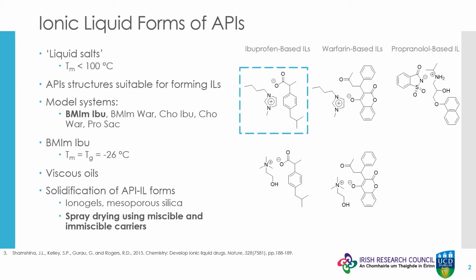Ionic liquids are a class of compounds with a huge amount of promise for simultaneously addressing the issues posed by poor aqueous solubility of APIs and the issues of solid-state instability by forming a thermodynamically stable liquid form of the drug. As APIs are often large, bulky, asymmetric molecules containing aromatic and ionizable groups, they readily lend themselves to forming ionic liquids. To do this, we can exchange the metal or halide ion of a conventional salt for one such as an imidazolium or cholinium ion, or even look towards artificial sweeteners such as saccharin to form ILs with cationic drugs. However, as ionic liquids are often viscous oils or hygroscopic waxes at room temperature, there are still considerable barriers to be overcome if they are to be routinely incorporated into solid dosage forms.